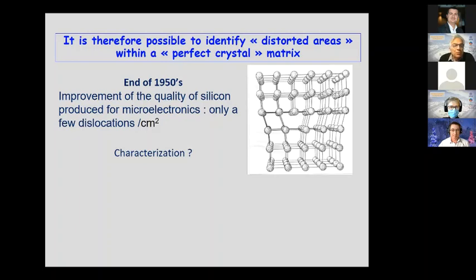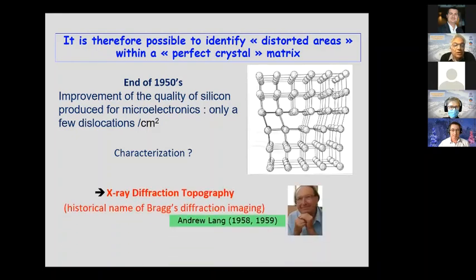At the end of the 50s, there was a tremendous improvement of the quality of silicon produced for microelectronics. Since that moment, transmission electron microscopy was the best technique to look at the dislocations in silicon. But when you had only a few dislocations per square centimeter, electron microscopy was no longer adapted. So how to characterize these crystals? Well, X-ray diffraction topography was implemented by Andrew Lang and went into practical use to characterize mainly semiconductor crystals, but after that was extended to all kinds of crystals.